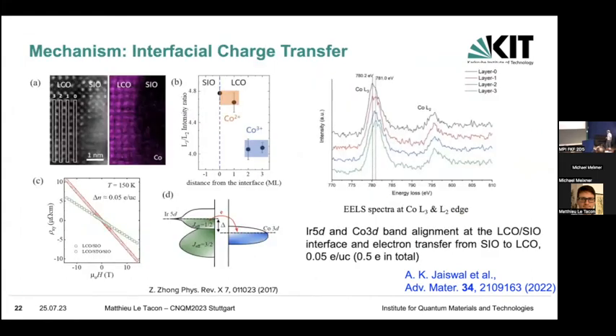Good. So the question is what happened there? And what we found is that there's actually a charge transfer from the iridium to the cobalt. More specifically, by looking, for instance, at the slope of the Hall effect at high temperature, so above magnetic ordering, we see a change of the slope, which tells us that about 5% of an electron is transferred from the iridium to the lanthanum cobaltate.